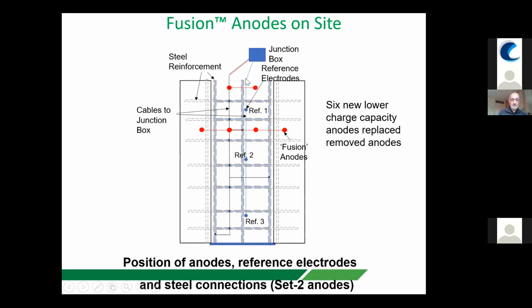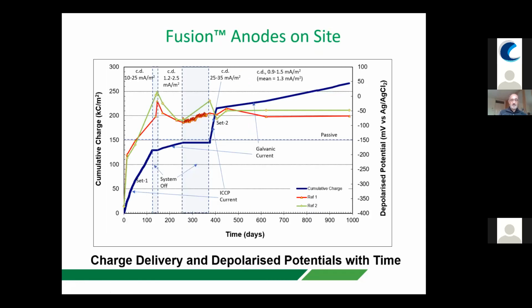We then went back and included some more anodes at the same place. This one with the smaller batteries, because we'd already passed quite a lot of charge to the steel reinforcement. And that kind of summarizes the whole. It's a very busy sort of graph, but I'll try and break it up gradually. What we have here is the amount of charge that we delivered. This was the first stage, just before we removed the anodes. We then removed the anodes down here and introduced the new anodes, which had a shorter life because they were smaller batteries.